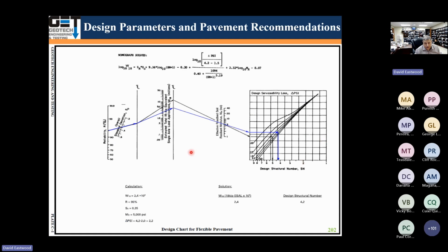Going through the pavement design by AASHTO, reliability of 95, overall standard deviation. In here, you have the transfer line. From that, you go to the traffic loading of 2.4 million. Then from that, you go to the effective roadbed soil resilient modulus of 5,000. That brings you right here. From that, you go to the design serviceability loss of 2.2 for this curve. That brings you down to the design structural number. In this case, our design structural number was 4.2.